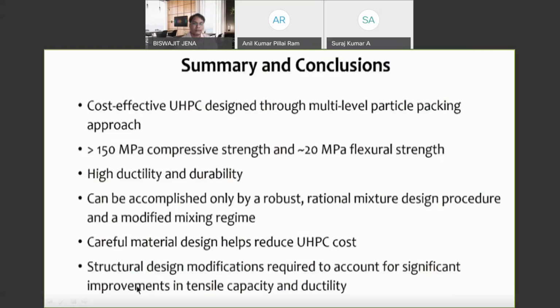There are issues with autogenous shrinkage, which has to be very well controlled by mixing in a self-curing material, and this can also be accomplished by a robust, rational mixture design procedure. You cannot do this using any other standard available methods, where generally the main parameter is the water cement ratio. Here the water cement ratio is basically a secondary parameter. First we always have to look after the packing of particles. The water cement ratio is that which is required to make this flow and fill.